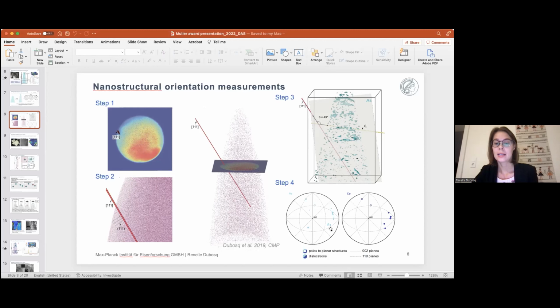I really do think that this could be a very robust method depending on the material that you're studying. So with geomaterials it's usually very difficult to get crystallographic poles or crystallographic planes within your 3D reconstructions or your data sets. So the fact that I was even able to get this trend with pyrite was really an achievement, I think. But I think we could easily apply this to other materials that may have clearer detector event histograms, and this would significantly reduce the error. And the more research we do and the more we optimize 3D reconstruction parameters, I think the more accuracy we can get with this approach.